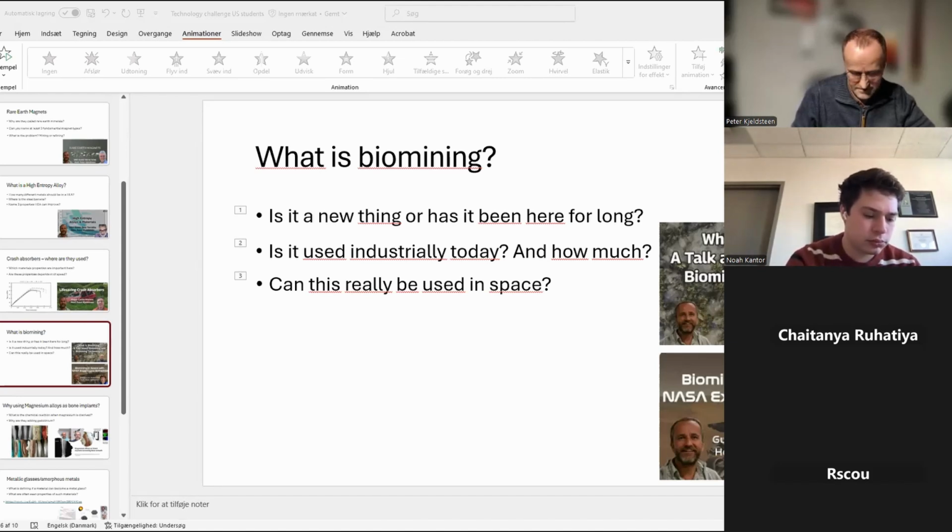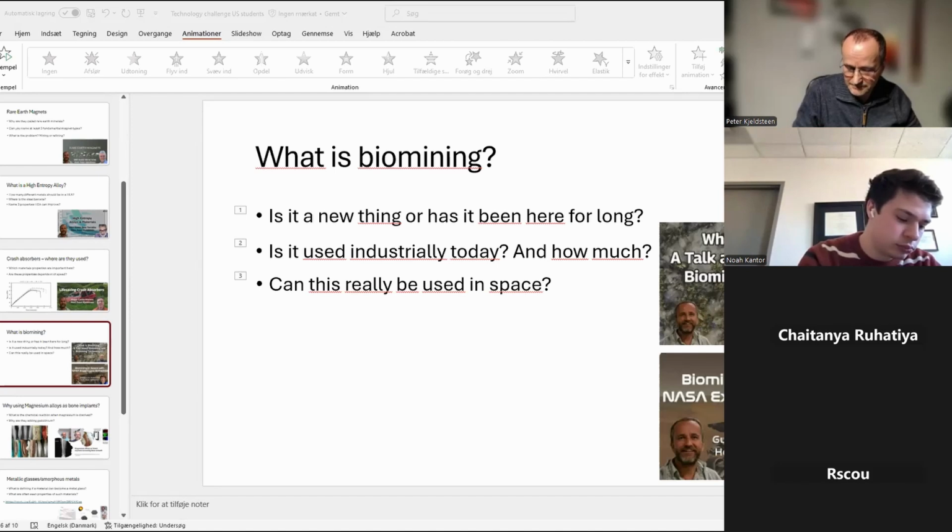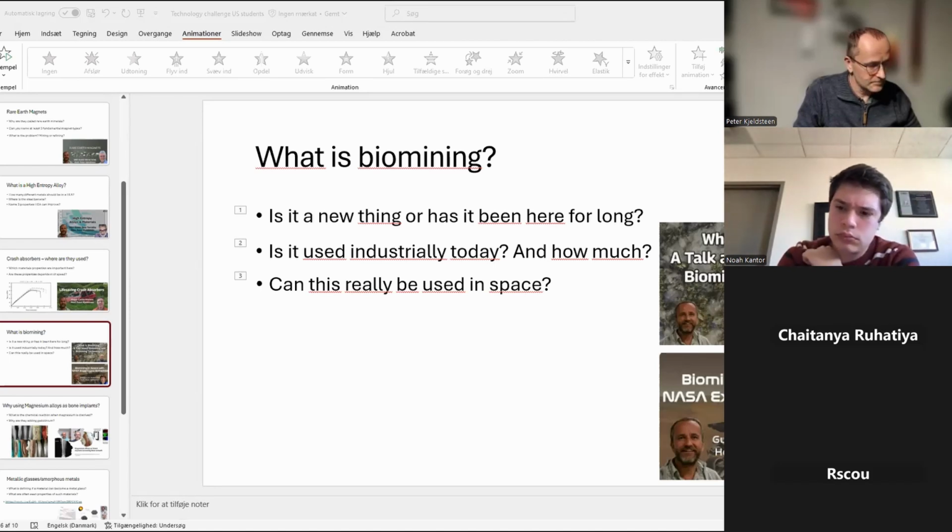So we have a culture of bacteria. There are different classes of bacteria. So we grow this bacteria in an environment, and then expose the spent batteries. So we cut open the batteries, we spread it out, and we dump the raw material of these batteries into the tub with the bacteria colony, where we let it grow under some humid environment, varying different parameters like temperature, the volume ratios, I mean the water and the solution ratios, different acid conditions like oxalic acid, basically varying that acid concentration.